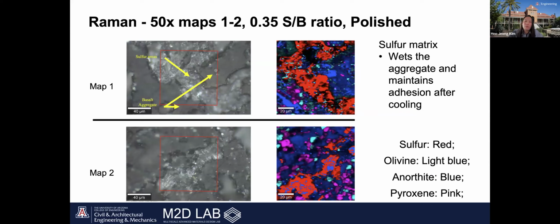And from the Raman mapping results, we found that the sulfur had very limited chemical interaction with the basalt powder, and there was no evidence of sulfide formation along the particle boundaries, which means the sulfur mainly acted as a binder rather than chemically reacting with the base materials. And this result suggests the bonding in sulfur cement is largely physical, and the overall performance depends more on mix design and compaction than on chemical reaction.